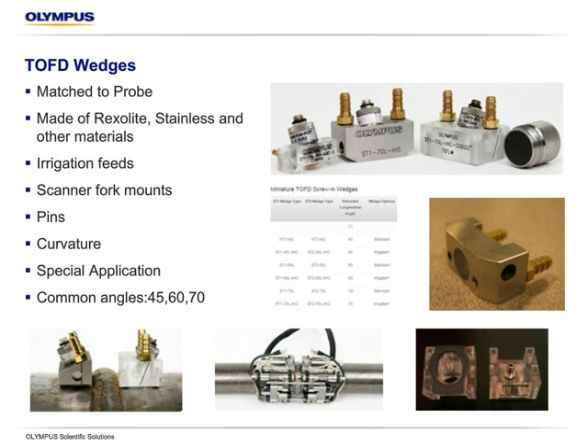Typically fed with irrigation ports so that we can have water flowing through them to act as our couplant, very consistent couplant. Forks to mount on the scanner. Some have adjustment pins so we can set the height and leave a small amount of couplant underneath. Other ones, like the stainless ones pictured here, can ride directly on the component without the use of a pin. Not have to worry about too much excessive wear like the plastic would wear over time.